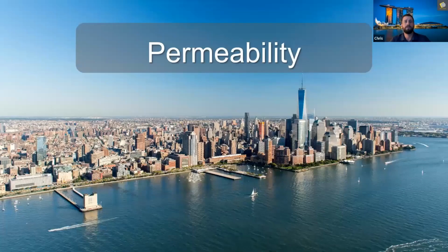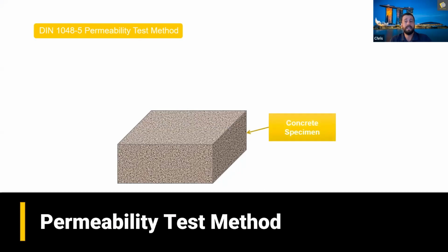Now let's take a closer look at performance testing to the critical elements of waterproof concrete, starting with permeability. So the DIN 1048-5 test method is designed to model concrete in the real world. This test and BS EN 12390-8 are equivalent and recognized tests that measure the depth of water penetration into concrete samples. Permeability tests require specialized equipment and cannot be done by all testing agencies. So products that are required to resist water under pressure must be evaluated using this test method.